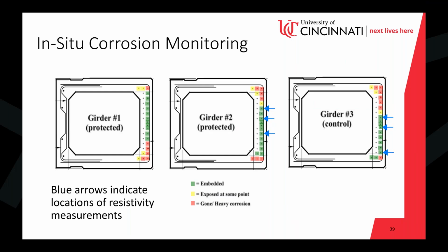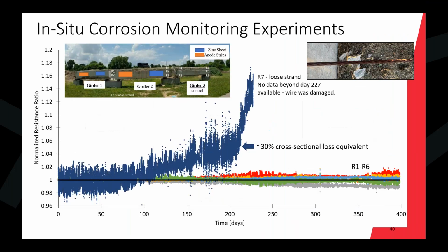What you will see is that, unfortunately, in the 1.5 to 2 years that we were monitoring, none of them experienced significant corrosion. But we did take a 7th strand and place it outside with the box beams, so exact same temperature conditions. You can guess which one it is. It's the dark blue data here, strand number 7. This is a loose strand that was just sitting out and exposed to the environment and corroding, and you definitely are able to pick up a response here.